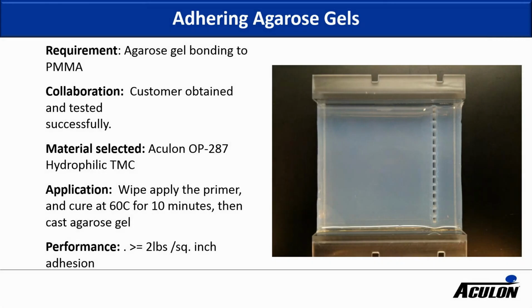And one last case study. This is one that we've recently commercialized, and it has to do with bonding agarose gel to PMMA. We found a hydrophilic TMC that was quite effective here. It was wipe applied to the PMMA surface, cured at 60C, and then the gel is cast, and we're getting good performance, greater than 2 pounds per square inch of adhesion. It's another good example of using our hydrophilic treatments for medical devices.